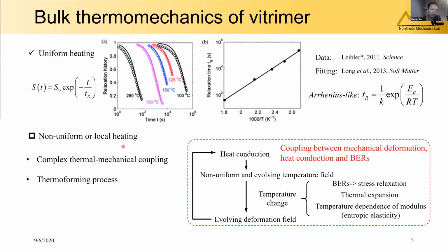for the non-uniform or local heating, the coupling between the mechanical deformation, heat conduction, and the chemical reactions can be more complex. The heat conduction causes an evolving temperature field. This can lead to an evolving deformation field in three aspects: the BER-induced stress relaxation, the thermal expansion, and the modulus change due to the entropic elasticity. So we will focus on studying the coupling between the thermal and mechanical, and study the thermoforming process. First, I will introduce the constitutive model developed by Long.